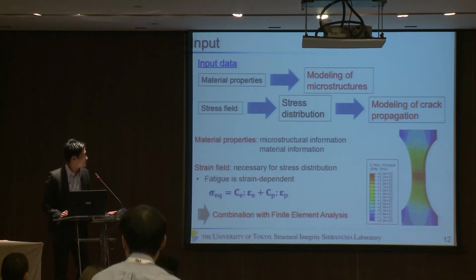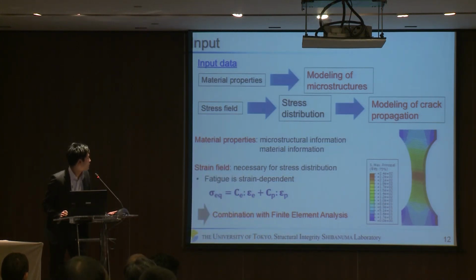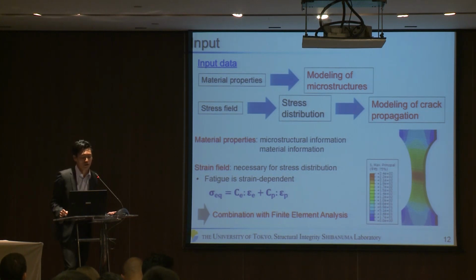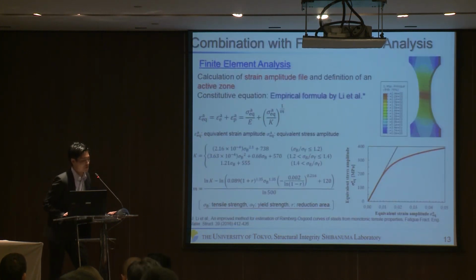Since the fatigue fracture is said to be determined by strain, the stress distribution is calculated from strain field in this model. To calculate the stress field, to obtain the strain field, in this model, finite element analysis is combined. In FEA, the effect of cyclic loading is considered. It is known that the stress and the strain relationship changes under the cyclic loading. So this equation is employed. So the effective stress distribution can be obtained by this equation.